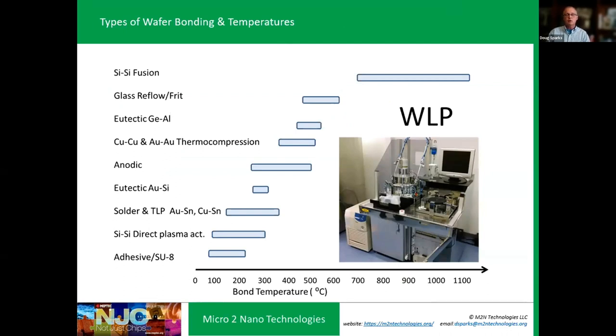On the left are the typical types of bonding technologies that are used, and then the temperature scale. If you're going to do silicon to silicon fusion bonding with annealing, MIT did this multi-wafer turbine stack at one time where they were direct bonding silicon and then annealing them to get the actual atomic diffusion across the bond interface. That's going to be done at maybe 1,000, 1,100 degrees C. You back that down, glass reflows probably at 400 to 425 C.